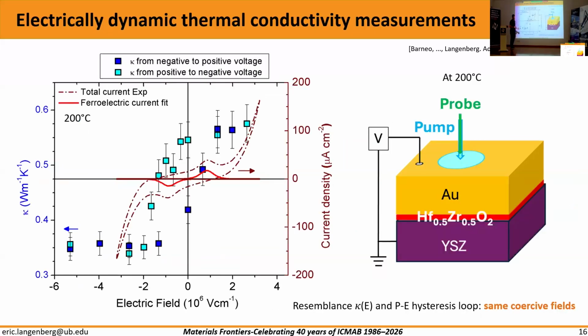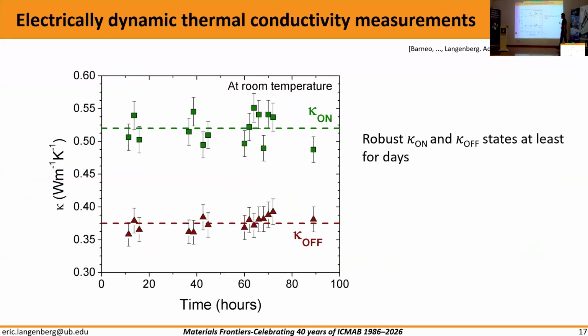And we also measure the polarization of this ferroelectric sample. This is the current versus electric field, and the coercive field in the polarization hysteresis loop coincides with the coercive fields of the thermal conductivity versus the electric field, which shows that the polarization is related to the thermal conductivity. And then at room temperature, because all these measurements were at 200 degrees, the two states, the thermal conductivity on and off state, remain stable for at least 4 days.